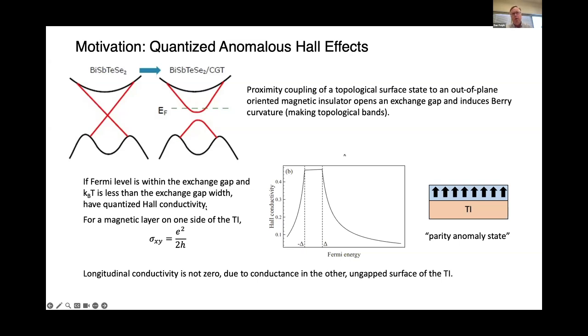If you just gap one surface of the topological surface state, just have a magnet on one side rather than both, you actually get a Hall conductivity of e squared over 2h. So half the usual value for a quantum Hall effect. And this is called a parity anomaly state.